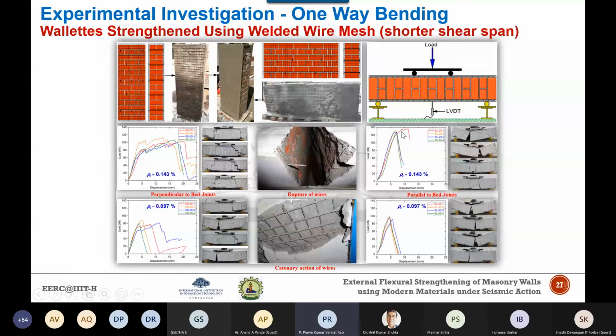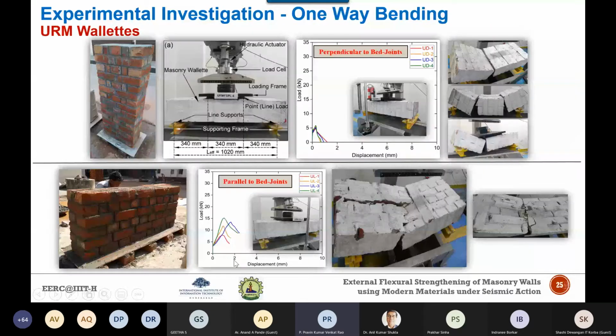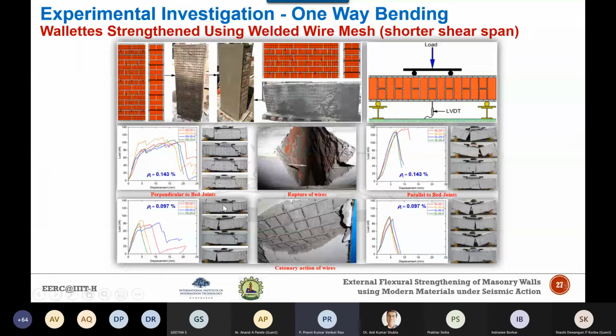Here you can see the maximum displacement this specimen can take is almost 1 mm. In case of parallel to bed joint, it is about 2 to 2.5 mm. But especially for wire mesh, the maximum displacement has reached up to 25 mm. Here 20 mm. So the deformation capacity is also larger. And even the energy absorption capacity, which is the area under the stress strain curve, has also tremendously increased.